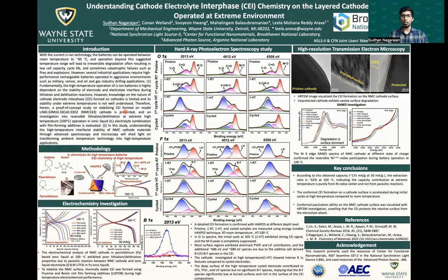Fundamentally, the electrolyte interface is the main source for degradation in terms of cathode. Cathode electrolyte interface is crucial. Understanding the cathode interface chemistry at high temperature is not well understood. Therefore, we investigated a layered model NMC cathode in a thermally stable ionic liquid environment, and we investigated the surface and bulk properties using various spectroscopy and microscopy probes.